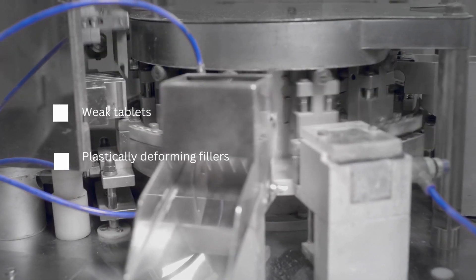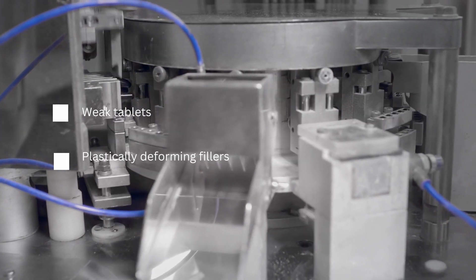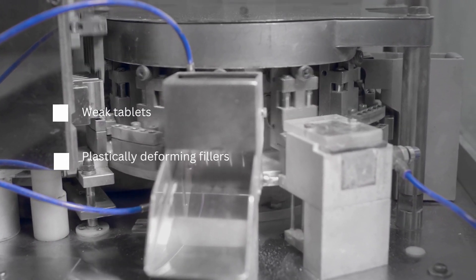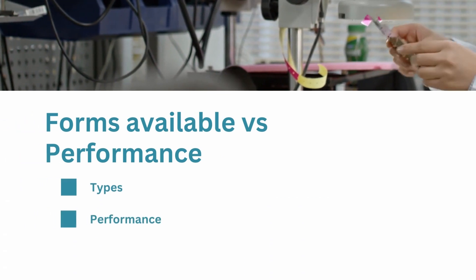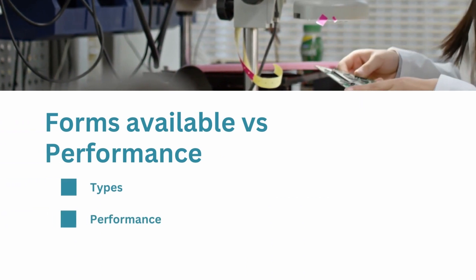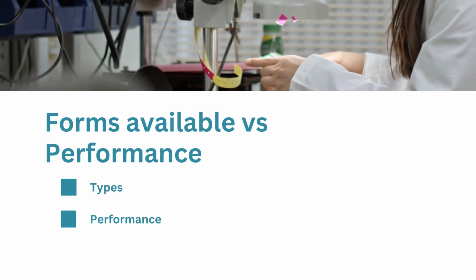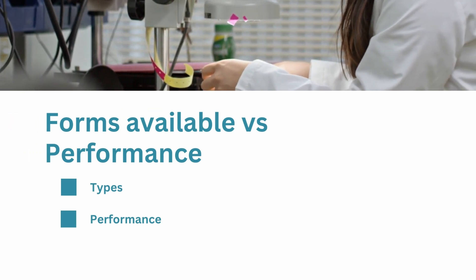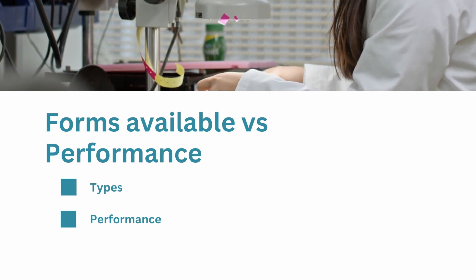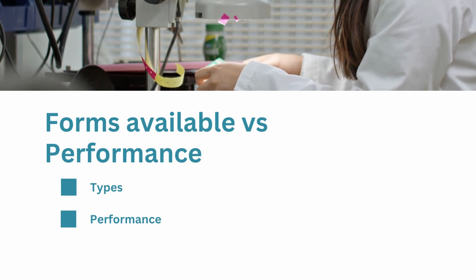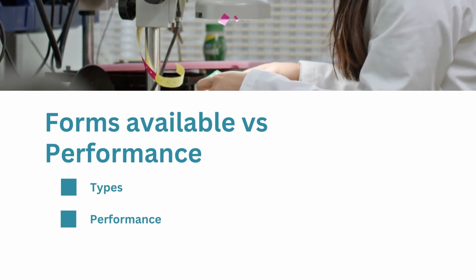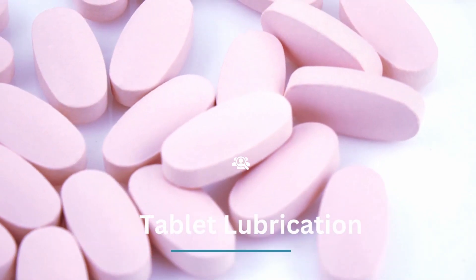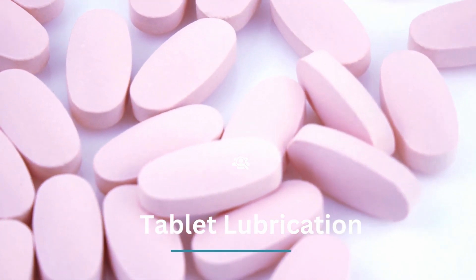In addition, when used with plastic-deforming fillers, it can lead to tablets of low breaking strength and high friability. Commercially available grades of magnesium stearate are generally a mixture of crystalline forms, mainly the anhydrate, monohydrate, dihydrate, and trihydrate. Depending upon the source, the material can differ in morphology, crystallinity, variability in particle size, surface area, and fatty acid composition. These differences can result in different compression profiles and lubrication efficiency, and potentially differences in hardness and tablet friability.